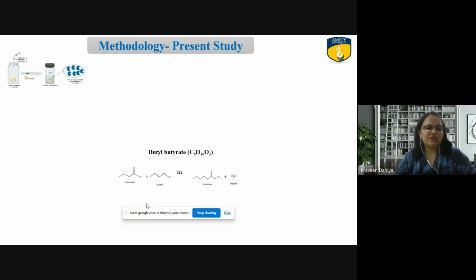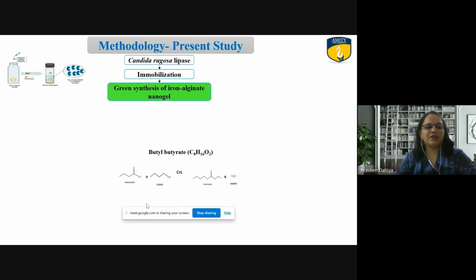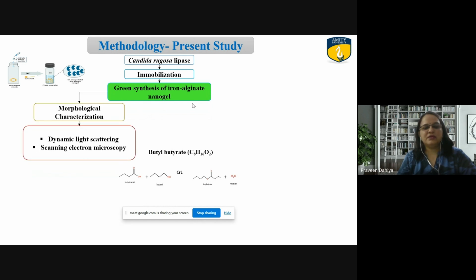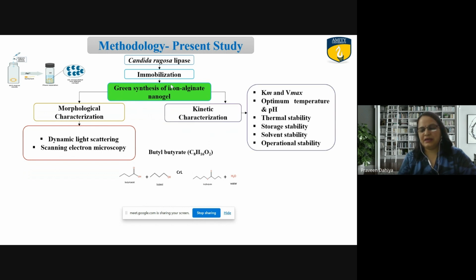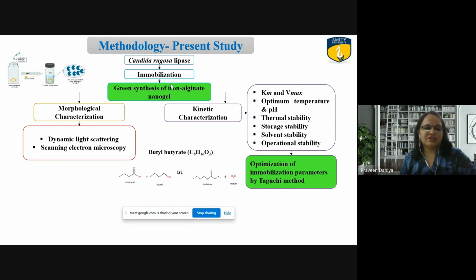Moving on to the methodology. Previously, iron alginate nanogels were synthesized through water in oil microemulsion method, where organic solvent hexane was used. Now, in the present study, we have replaced the organic solvent hexane with a vegetable oil, that is virgin coconut oil, so as to have a green synthesis of iron alginate nanogel. Furthermore, the synthesized iron alginate nanogel was morphologically as well as kinetically characterized, where several aspects were studied. This is then followed by optimization studies using Taguchi design and L16 orthogonal array, where immobilization parameters are optimized for Candida rugosa lipase synthesized using green technology.